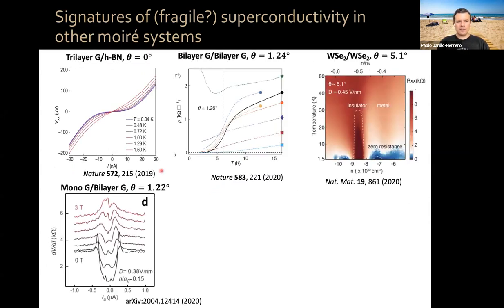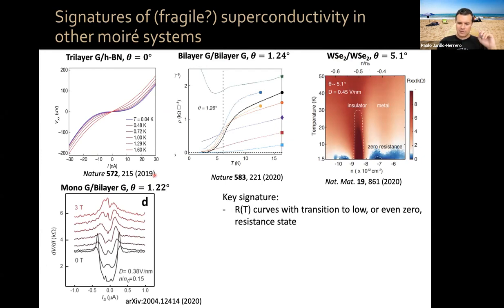Now, this robust superconductivity is in contrast with signatures of what is perhaps fragile superconductivity, and some people don't even know for sure if this is superconductivity or not in many other Moire systems. In all of these systems, trilayer graphene aligned to hBN, bilayer graphene twisted on top of bilayer graphene, twisted transition metal dichalcogenides, twisted monolayer-bilayer graphene, people have reported observations which are consistent with superconductivity. For example, resistivity versus temperature curves which go down at some point, they have this knee-type behavior, and sometimes they even go to zero resistance.